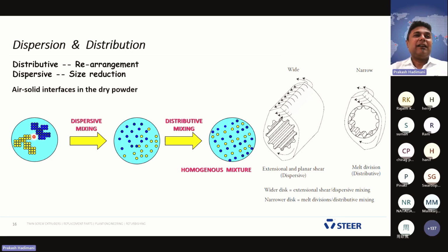In this case, these are the agglomerated particles. Here is a blue and a yellow. If you disperse by using a kneading block, the blue pigment and yellow pigment are separated out into two halves. Then again, this blue and yellow has to be mixed together. That is the mechanism we call distribution. The first one, breaking agglomerates into smaller and smaller, we call dispersive mixing.